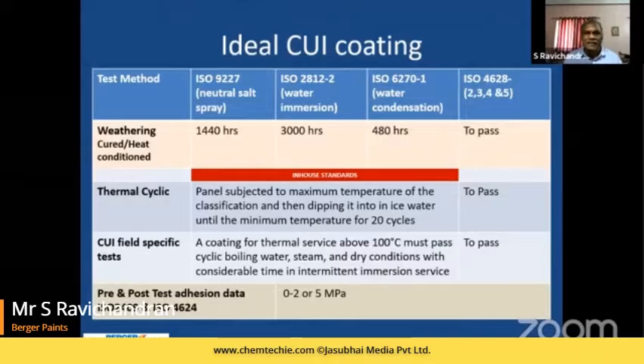When you talk about thermal cyclic, it is more of an in-house standard wherein we subject it to 10 cycles or 20 cycles and try to understand what happens when there is going to be a thermal shock or a change in temperatures. The corrosion under insulation field specific test is a very interesting one, and we require a coating for thermal service above 100 degrees. It should not only take care of cyclic boiling water, but also handle steam and drying conditions with considerable time in intermittent immersion services. And we are projecting those data as a very aggressive test, which a coating is able to pass through, to perform ideally under an operating condition.